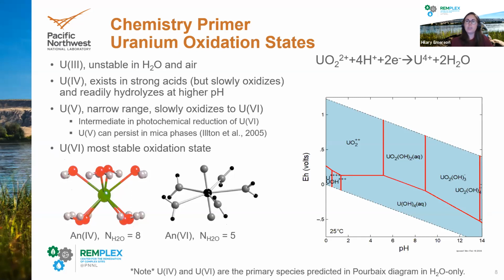They both have quite different behavior in the environment, with the +4 oxidation state having a fairly low solubility and a fairly high complexation affinity and sorption affinity, with the +6 oxidation state also having a pretty high complexation affinity, but lower sorption affinity and higher solubility. So we often see uranium-6 in solution and uranium-4 primarily in the solid phase. On the right here, I have a Pourbaix diagram of uranium speciation in pure water. The dotted lines on this figure represent the stability field of water, and each of these areas represents the major uranium species under those conditions.